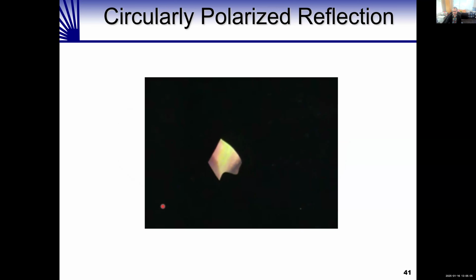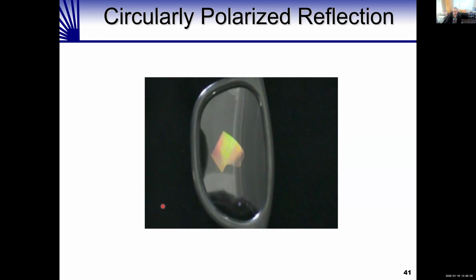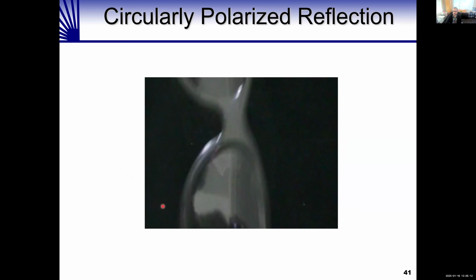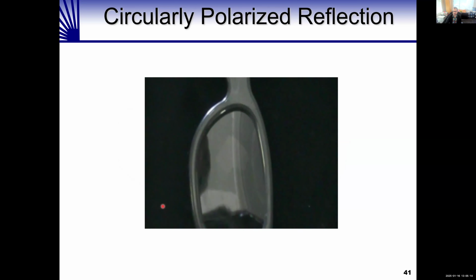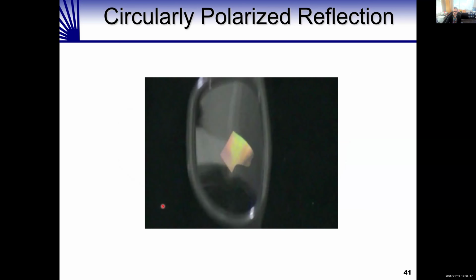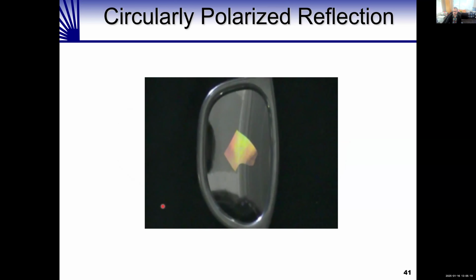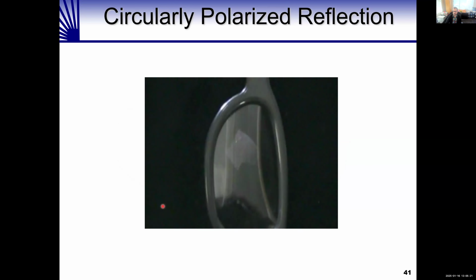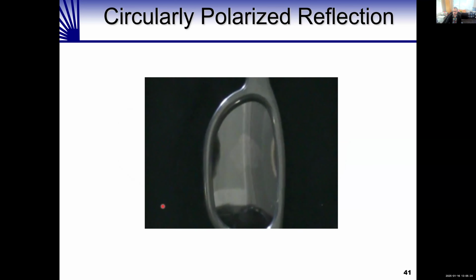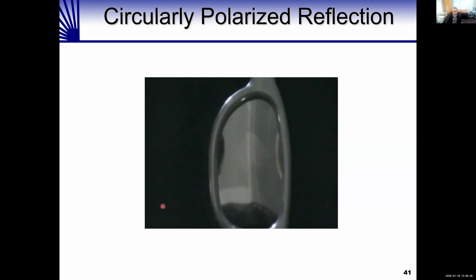This is a sample of chiral nematic mesoporous silica. Through one lens, it looks perfectly normal, but it completely disappears through the other lens. This shows a really interesting physical property of our materials: because they have a left-handed helical structure, they only reflect left-handed circularly polarized light.